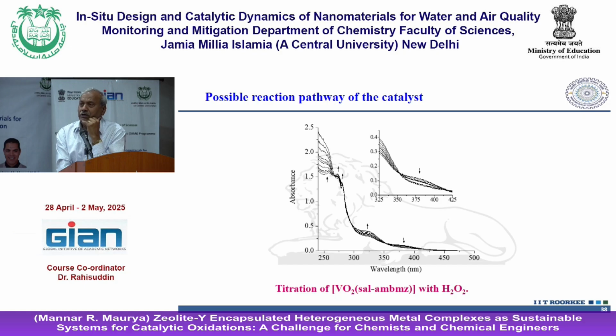We could also record the 51 vanadium NMR, but here the material is not suitable for vanadium NMR. So we are restricted to only UV visible spectroscopy, but the isosbestic point is very helpful in concluding that the dioxo species is converting into an oxoperoxo species, and then the oxygen of the oxoperoxo is transferred to the sulfide, converting it into sulfoxide and sulfone.